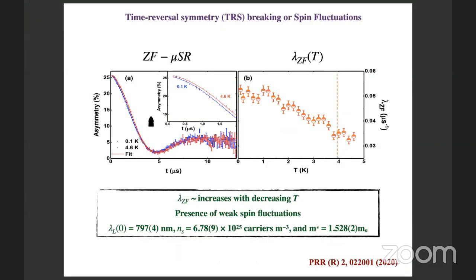And this is the zero field asymmetry spectra below and above the superconducting transition. We have fitted these spectra using an exponentially decaying Kubo-Toyabe function and plotted the relaxation rate as a function of temperature. It is clear that the relaxation rate decreases with increasing temperature. So this suggests the presence of spin fluctuations in this system.